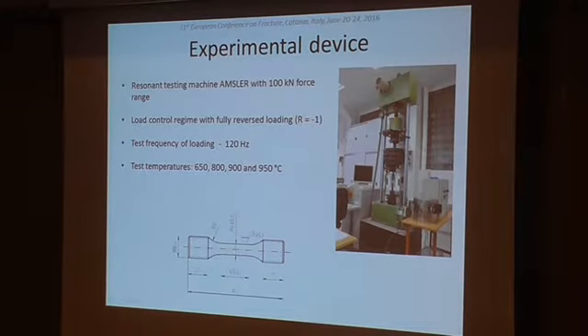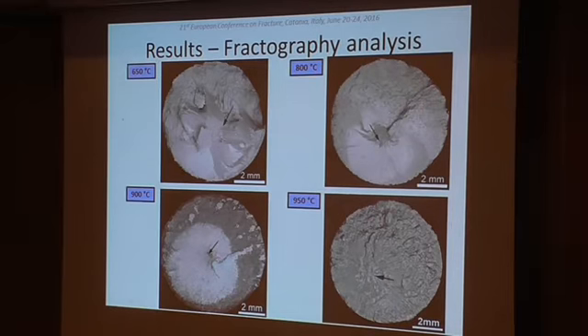All fatigue tests were done on a resonant testing machine Amsler in a load control regime with fully reversed loading. Test frequency was 120 Hertz, and we had 4 test temperatures: 650, 800, 900, and 950 centigrades. Here come first results.